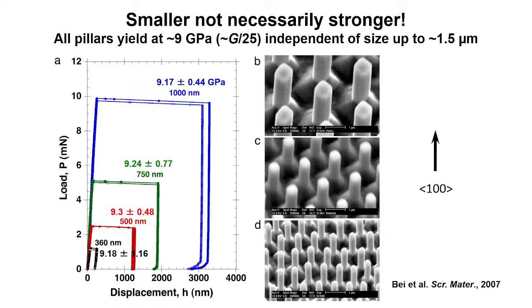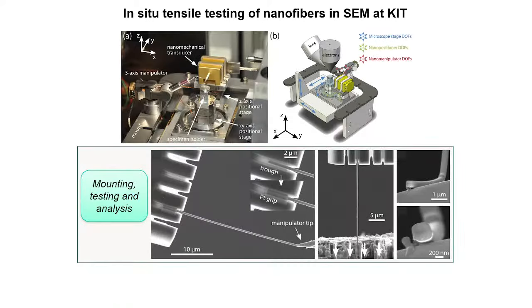So if you look at the compression pillars, right? The data are scattered, but not very badly scattered. They're all about 9 GPa plus or minus a tenth of a GPa or something. But the tensile yield strengths are scattered quite a bit. Right? So they go all the way from what you would expect a bulk to behave like to what a perfect crystal would behave like. And the reason is because the size of this pillar is different from the size of this fiber. This fiber is quite a bit longer than this. And so the probability that you would find a pre-existing defect in this is much greater than in here.